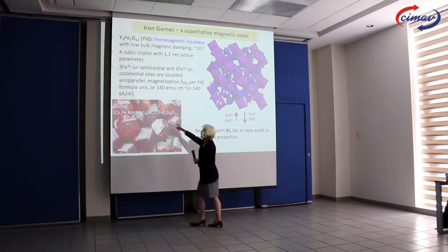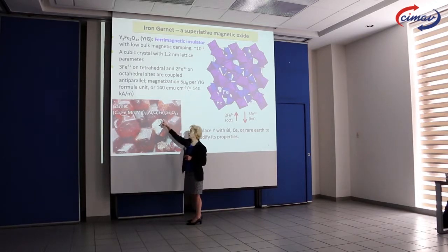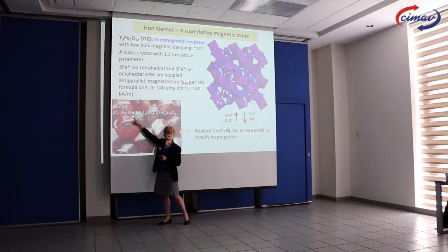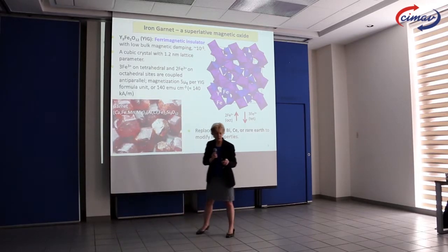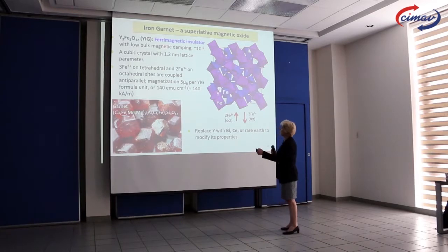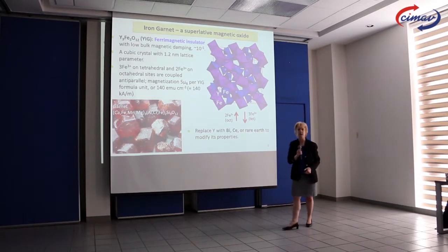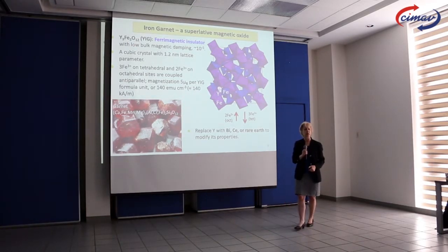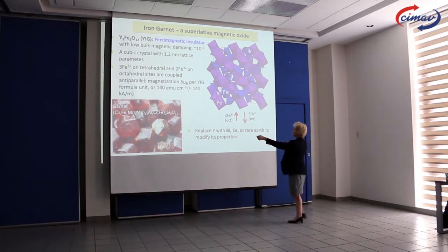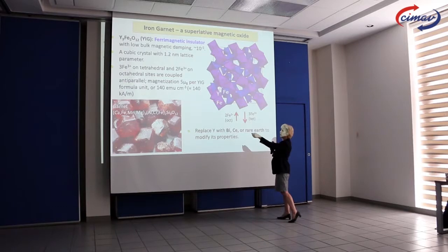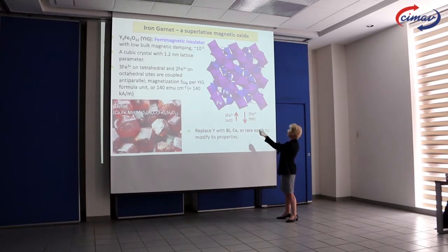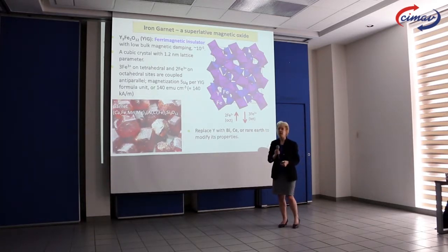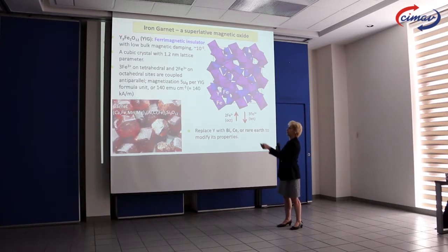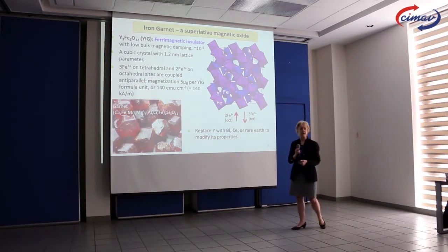So this is the most common formula, and it gives you that red colour. If we take the silicon and replace it with iron, and if we put something else in this site like yttrium, we get an artificial garnet, and this is YIG, yttrium iron garnet, Y3Fe5O12. This is the same crystal structure as natural garnet. And there's a picture of the crystal structure. It's actually quite complicated. You can see octahedra. This is an octahedron of oxygen with iron in the middle. This is a tetrahedron of oxygen with iron in the middle. And then these sites here, these dots, represent the site where the yttrium will sit. So we have three different kinds of lattice sites in this garnet.